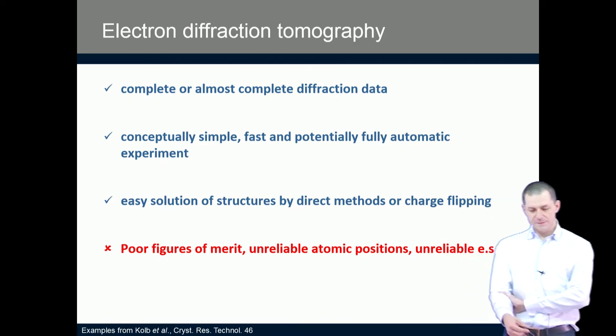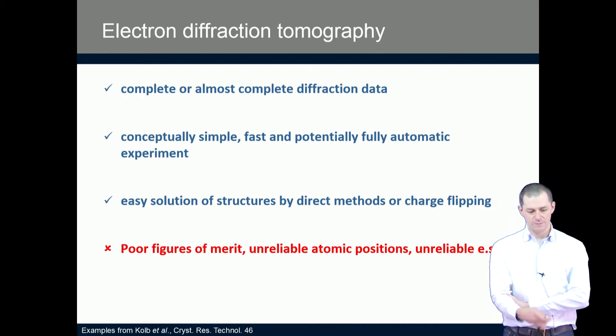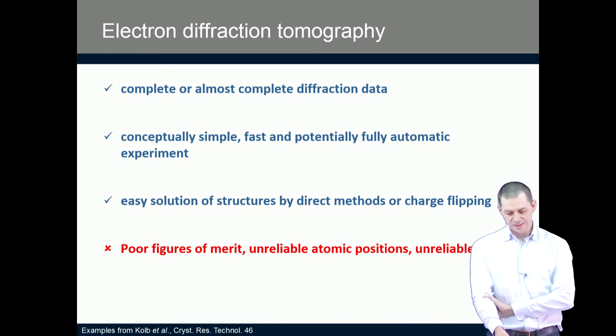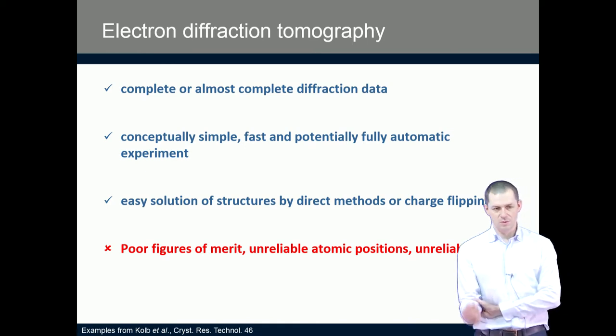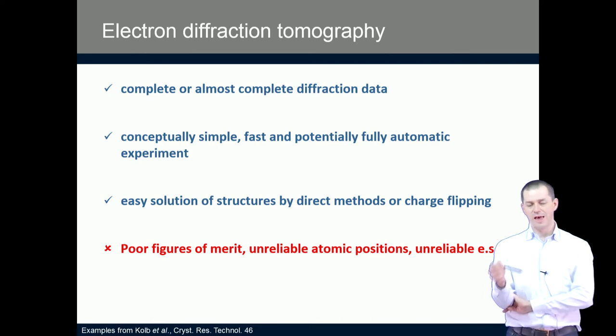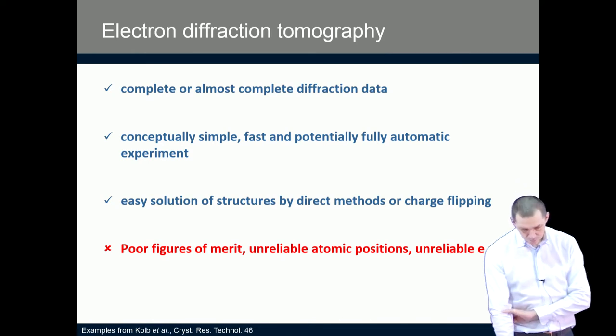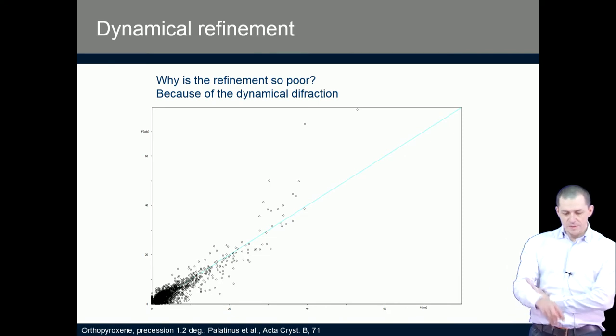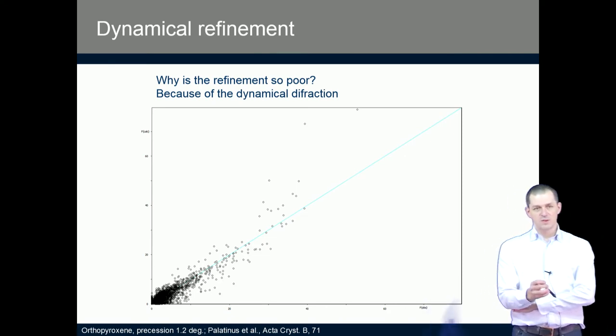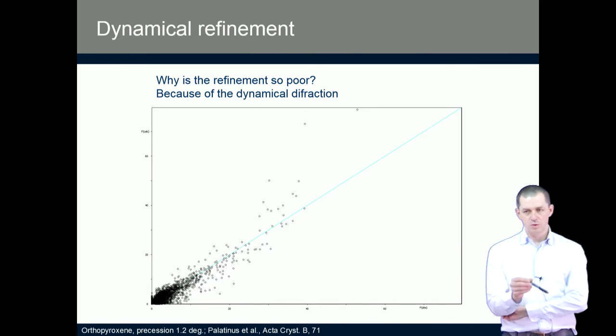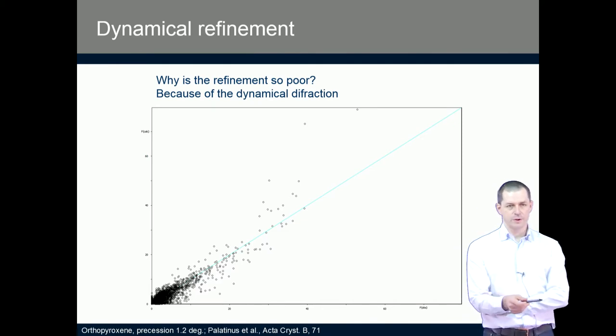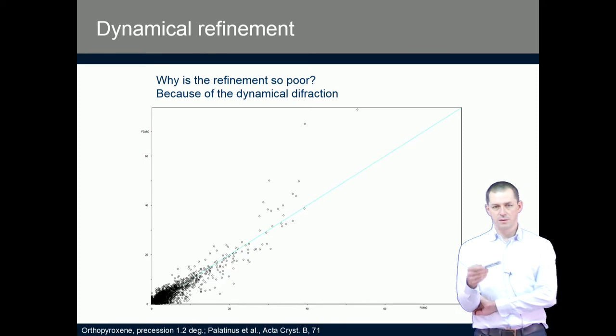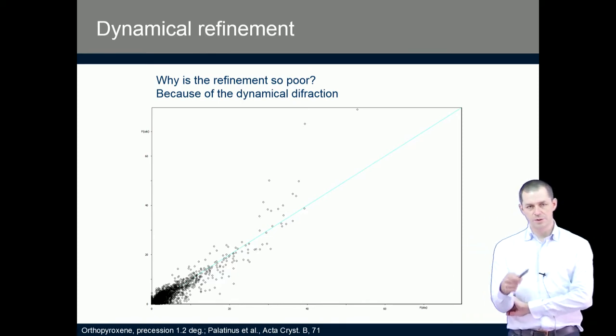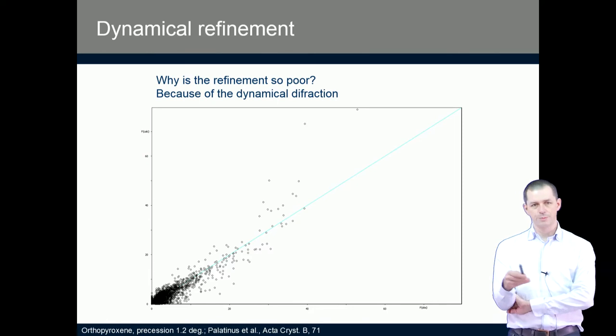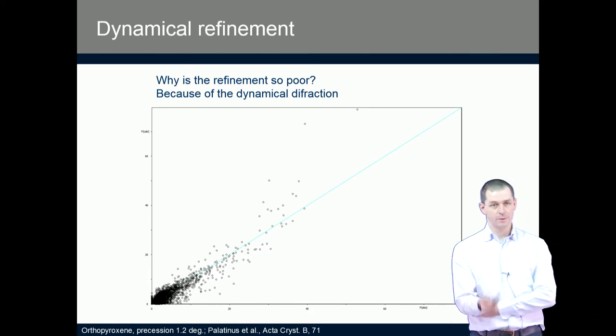Unfortunately, the refinements are not so easy. They give poor figures of merit, unreliable atomic positions, and unreliable ESDs, estimated standard deviations. So there is an uncertain accuracy of the result. And the reason for the poor figures of merit and not so good fits is the dynamical diffraction. Even if you combine the data collection with precession, which tends to suppress the dynamical effects, even then the dynamical effects are there.